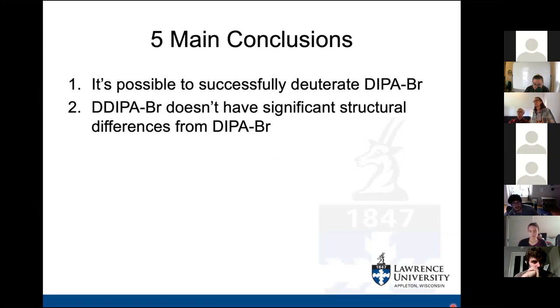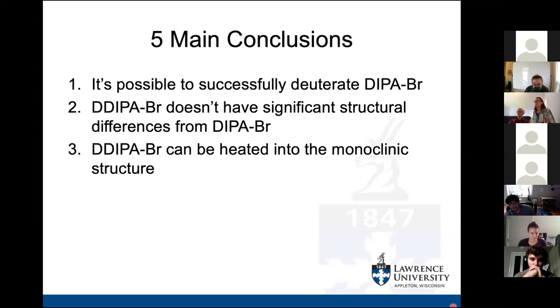The NMR and X-ray diffraction spectra were compared to the spectra of the non-deuterated Diisopropylammonium, and aside from the decrease in the amine, or ND2 peak of the NMR, which is to be expected since deuteriums don't give off a signal in proton NMR, the remaining parts of the spectra are unchanged. 3, deuterated Diisopropylammonium can be heated into the monoclinic structure, just like Diisopropylammonium can. This is especially important because, with deuterated Diisopropylammonium being able to exist in the monoclinic structure, more extensive tests can be done on it to see if it is in fact a ferroelectric crystal.